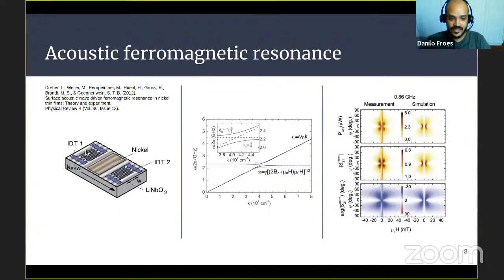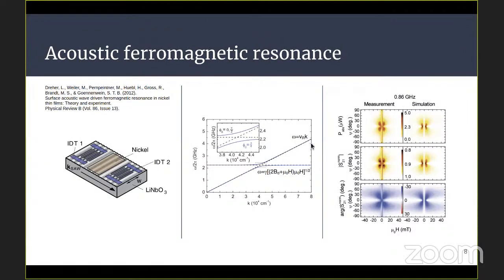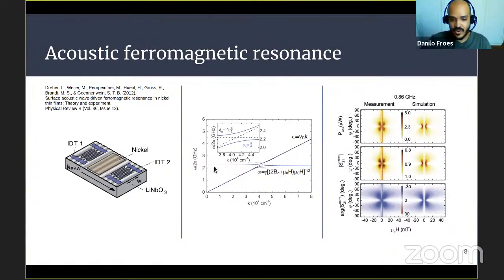So here, two interdigital transducers with a nickel film, which is magnetostrictive. One of them is the elastic dispersion, which is this straight one, and the magnetic, which is this almost without a slope here. They suffer a crossover due to the magnetoelastic interaction. So we have a magnetic curve that becomes an elastic one, and the other branch is the opposite. This is one of the characteristics of these excitations, these hybridizations.